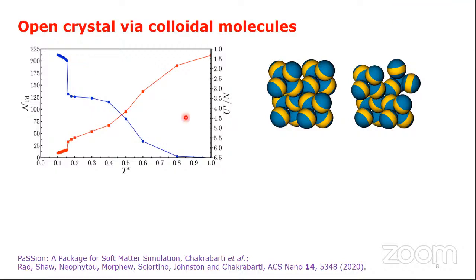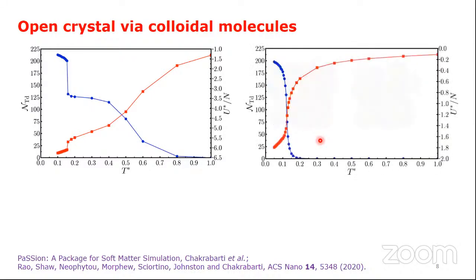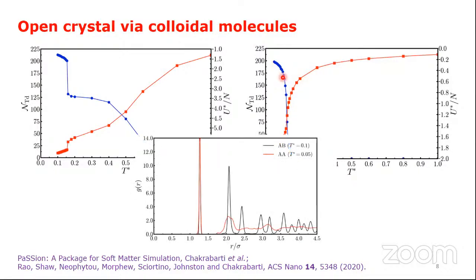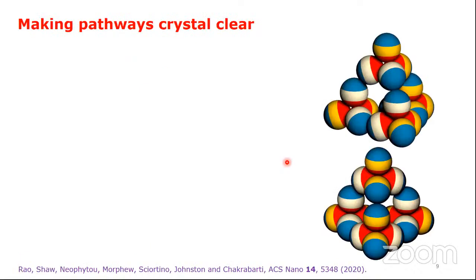However, our Monte Carlo simulation studies yield amorphous structures, though with a comparable number of tetrahedra. The pair distribution functions for the sets of tetrahedra show that no long-range order emerges in the absence of a hierarchy of interaction strengths, in which case we talk about AA tri-block patchy particles. A pertinent question is how hierarchical self-assembly pathways promote crystallization in this case.